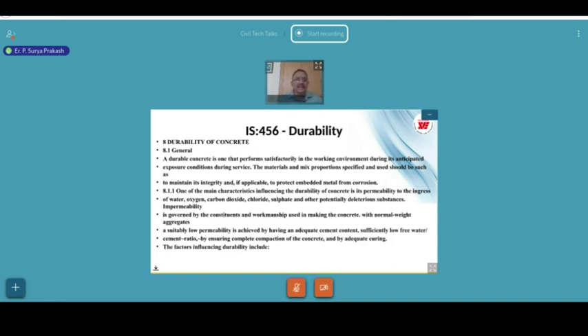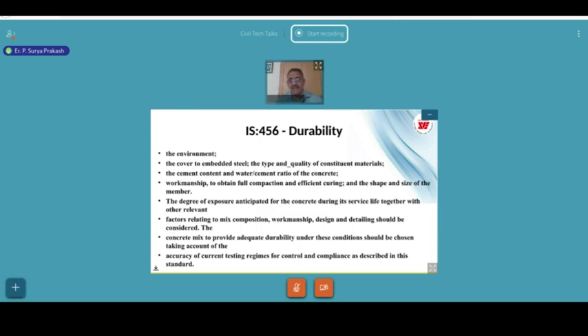So the durability criteria of IS 456 are all talking about concrete cover and chloride penetration, and cement consumption, the minimum cement consumption that is prescribed depending on the exposure conditions. So these are all the durability provisions. So materials, the cement content and water cement ratio of the concrete, workmanship to obtain full compaction and efficient curing, and the shape and size of the members, that is minimum column size, minimum beam size, minimum slab thickness, minimum cover provisions, and workmanship and design detailing should be considered as per the codal provisions.